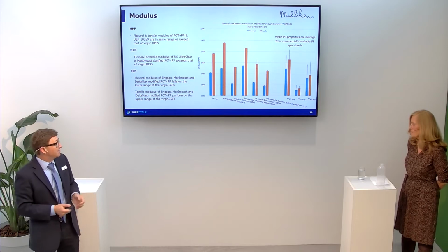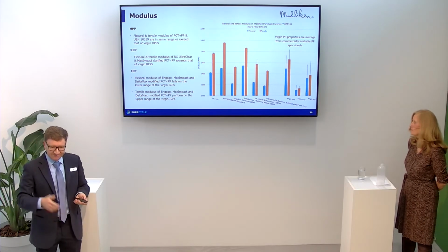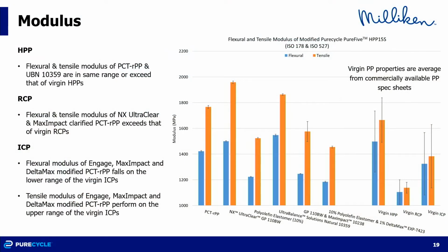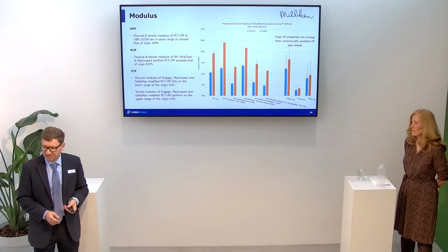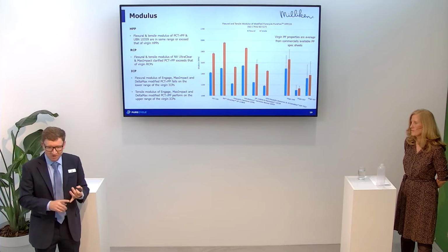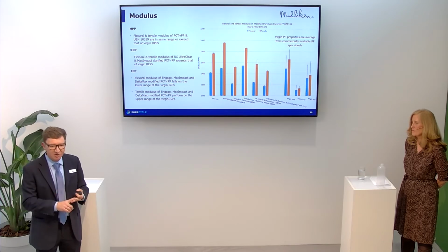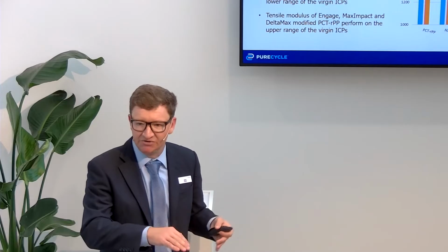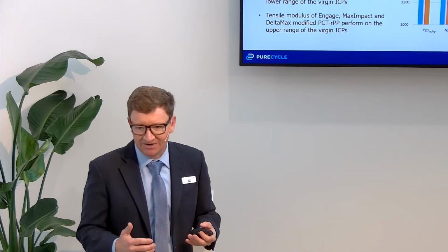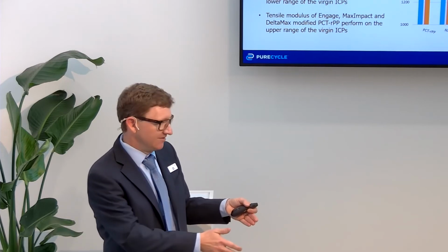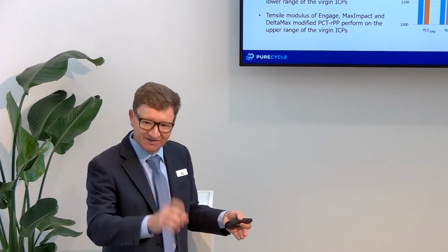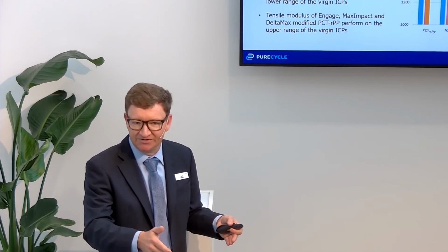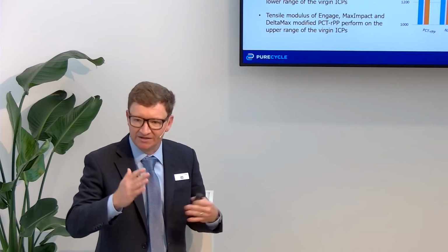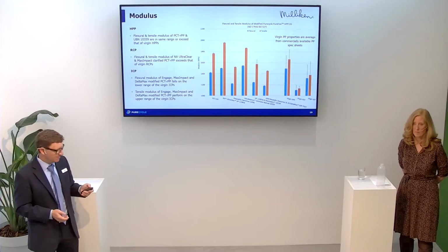So in terms of properties, what I did instead of just randomly picking individual polypropylenes to compare properties, for the virgin materials, we took about 50 different spec sheets for either homopolymer, a random, or an impact copolymer, averaged those numbers and showed the ranges. Because really we just want to say that the PureCycle material isn't comparative to a specific virgin material, but the properties fall in the appropriate ranges for what they're comparing to.